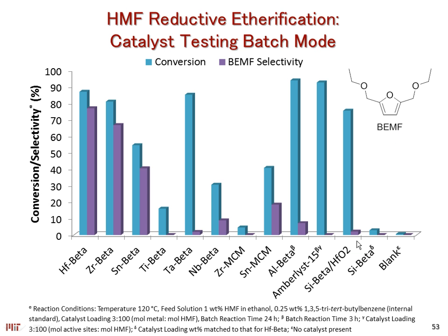In this case, we actually resorted, based on some of the properties of zirconium beta, to actually making a new zeolite called hafnium beta, so incorporating hafnium into the framework of the material. Hafnium has very interesting properties, actually very similar to zirconium, but a little bit stronger Lewis acidity, and we can discuss that after the talk if you'd like. But what we find is that actually hafnium beta in our initial batch screening is a very good catalyst for doing the hydrogen transfer step and the hydrogenation chemistry as well.